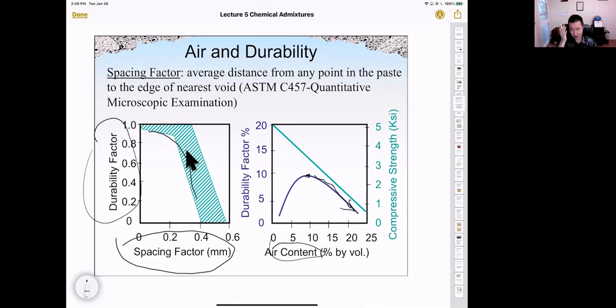The reason for that is, on one hand, more air lets us release more stress due to the freezing of the water. On the other hand, because we introduce too much air, that reduces the strength of concrete quite a lot. So we have a balance point, somewhere around 7 to 8%, where the concrete has the best balance between resistance to the tensile stress from the freezing of the ice and also the best strength, because with higher air content the strength goes down almost linearly. Again, with too much air, the strength of the concrete will be too low to resist the stress from freezing. That's why we have this optimal dosage for air, which is around 7 to 8%.